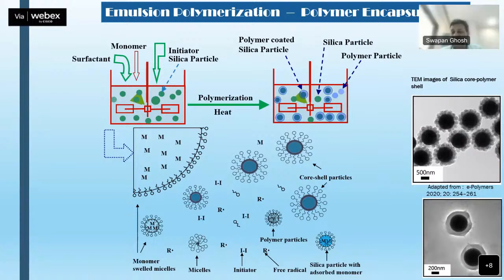So the morphology depends on the type of polymer that we are using. For example, if I use PMMA, we can have a very smooth shell around the particle. If I use polystyrene, then they will form some sort of necklace type of structure on the silica particles. And if I use cross-linking, then this type of polymer again will form a smooth layer on the silicon oxide particles. So depending on the type of monomer, depending on the type of cross-linking agent, the morphology can be played with. And based on the morphology, the final properties also can be varied.